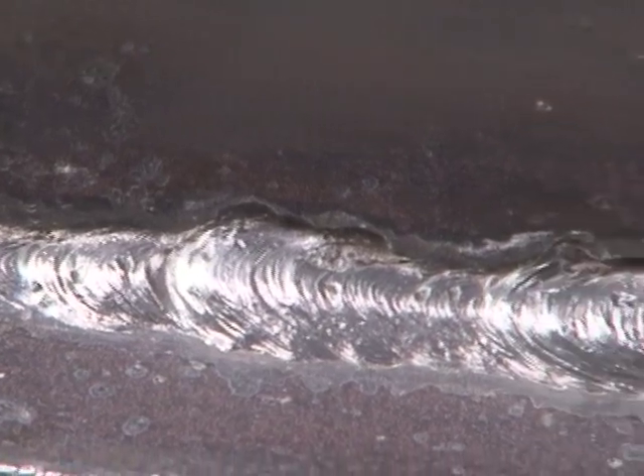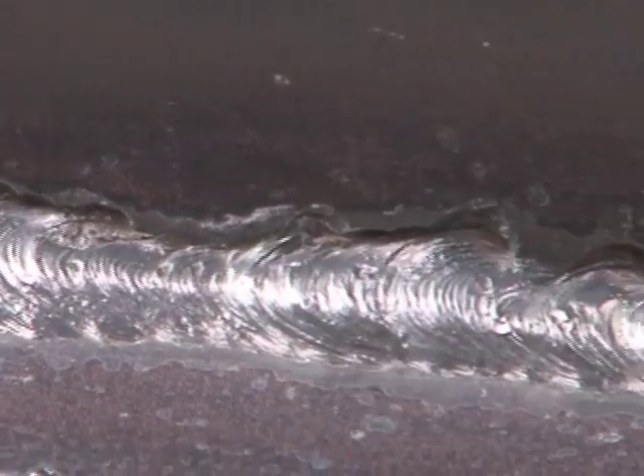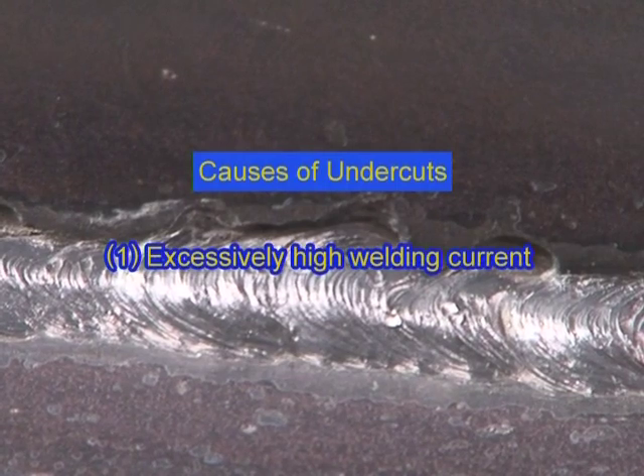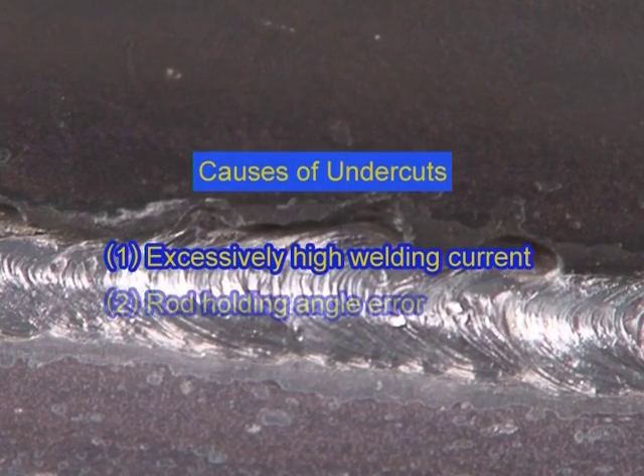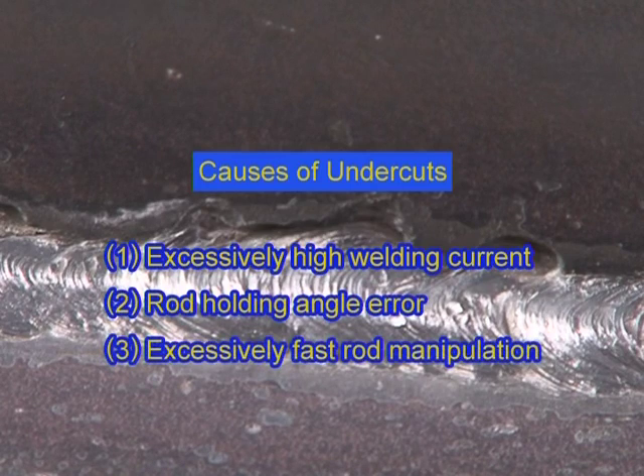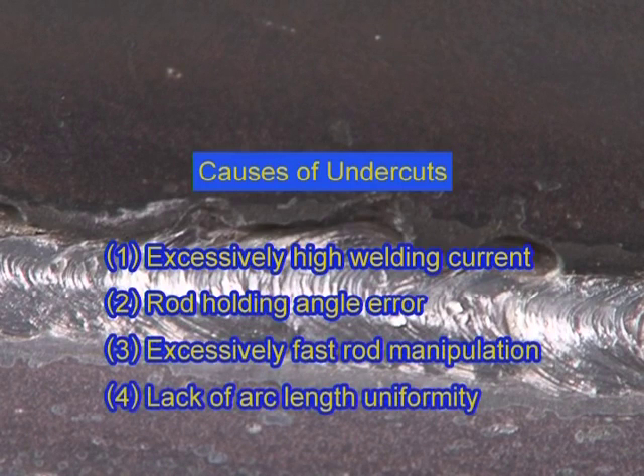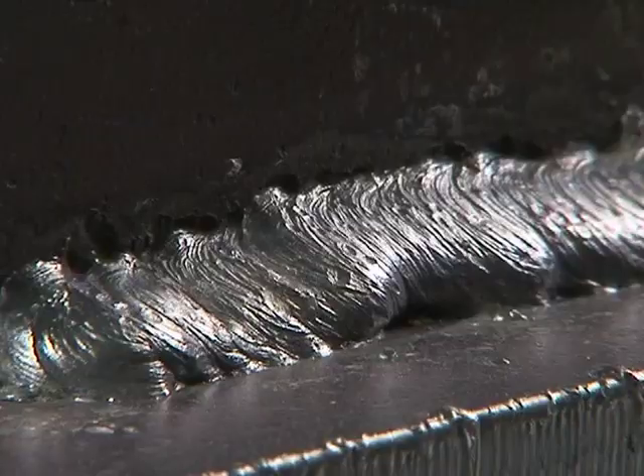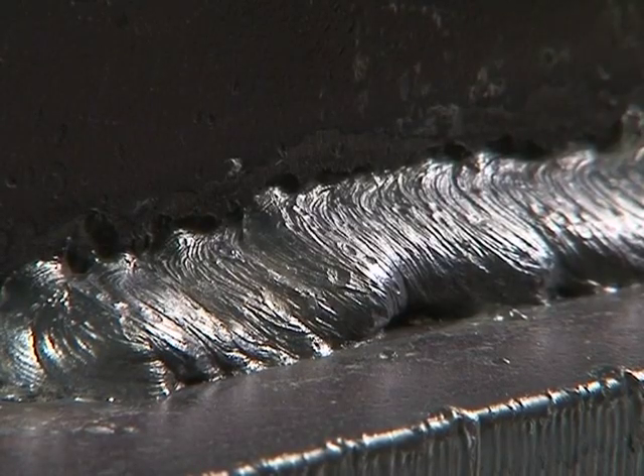Undercuts found at the weld toe on the vertical plate side can be attributed to causes such as too high a welding current, an error in the rod holding angle, excessively fast rod manipulation, and lack of arc length uniformity. Now check the horizontal plate.